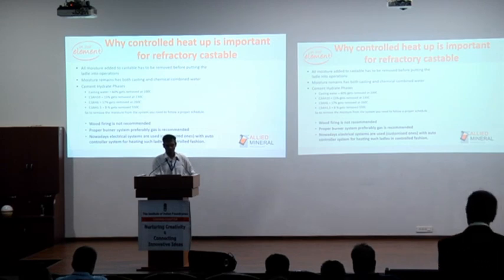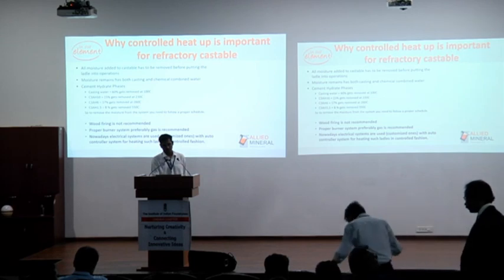So 60% of water gets removed at 100 degrees, 15% gets removed at 230, 17% gets removed at 260, and 8% at 550. So from 550 to 600 degrees Celsius, it is very critical, and utmost care has to be taken during this phase of dryout. We don't normally recommend wood firing, because with wood firing there's no controlled heat up. So the temperature rises drastically and it leads to cracks. So we always recommend either a burner or an electrical system for these types of ladle preheatings or dryouts.